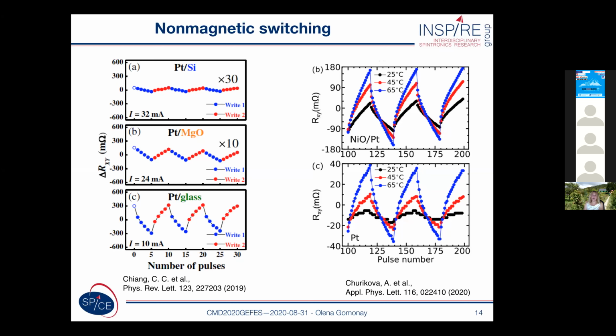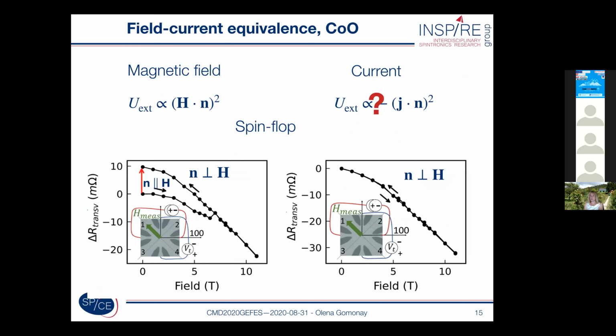Nevertheless, we decided to check whether the current can really create this potential force on the Néel vector. And for this, we decided to do the straightforward thing. If the current acts as a field, let's compare the action of the current with the action of the magnetic field, which is well known. So if you apply a magnetic field to an antiferromagnetic system, it can induce spin flop. And this spin flop means that if we start from the parallel orientation of the antiferromagnetic vector and field, then the Néel vector will be unhappy at some critical field and will try to flip perpendicular to the magnetic field, as can be seen from the left lower panel in the slide.